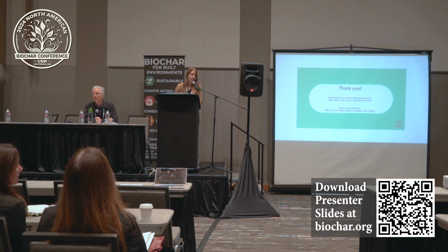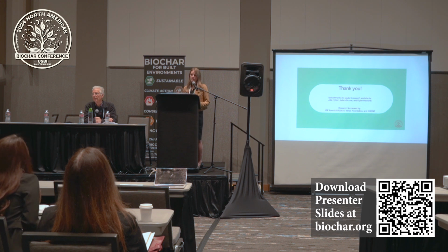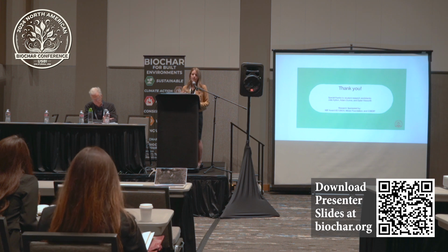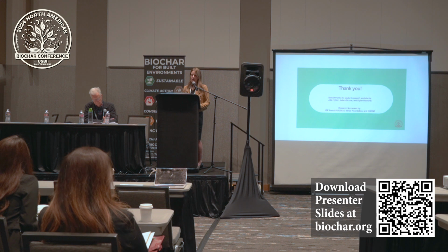Yeah, so those are great questions. The question was water to cement ratio. As I mentioned, that really controls a lot of the strength properties. We are not counting the biochar as part of our cementitious content. So when we do our water cement ratio, we're really basing it on the cement content that's in there. So if we reduce the cement content, we have a lower all around water demand. We are trying to compensate for ambient moisture in the biochar. So we tune for that. That will vary slightly depending on what we measure for the biochar.